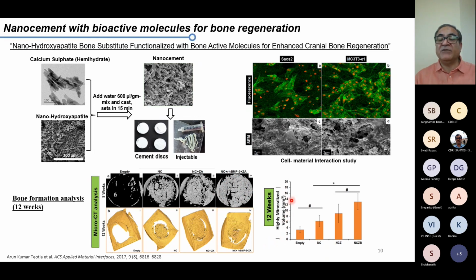You can also see quantified data here by bone volume and mineralization data. In the case where you have cement along with the bioactive materials, bisphosphonate as an anti-catabolic agent and BMP as an anabolic agent, they have yielded the best optimum results in 12 weeks. Cranial defects are complex to repair completely. But with these interventions, where you add such bioactive molecules, it is possible to completely regenerate even the cranial defects.